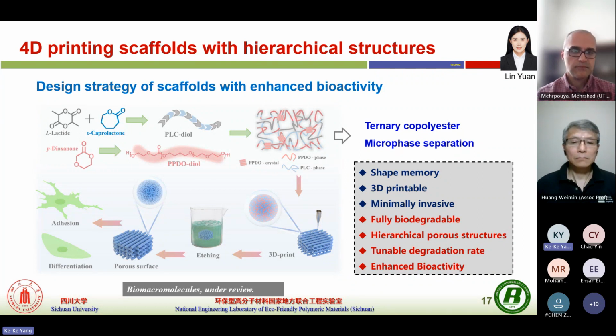It also can act as the switching segment. For the fixed segment, we introduce the PPDO, which is crystalline with a higher melting temperature. These multi-block polymers show distinct microphase separation morphologies, which allows us to create hierarchical structures.